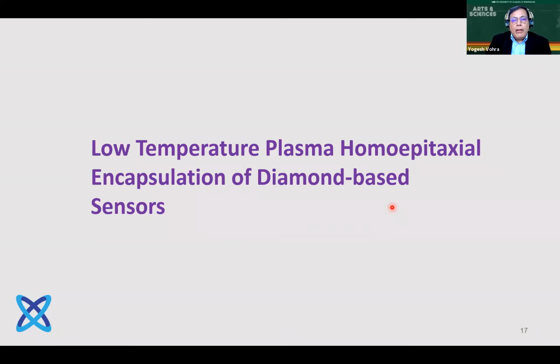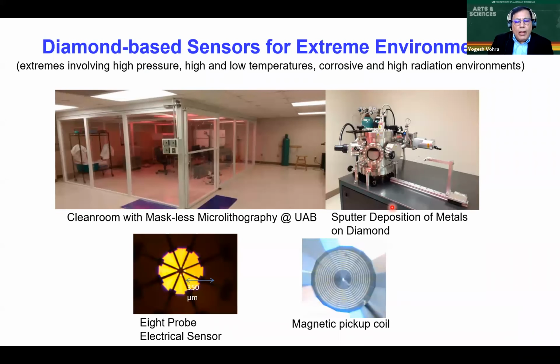Okay, so moving on to the next area about this homoepitaxial, continuing with the theme about growing diamond on an existing diamond substrate. We talk about homoepitaxial encapsulation of diamond-based sensors. So here we are going to do some lithography and actually put diamond sensors on top of a diamond crystal. So this is the Diamond Microfab lab at UAB. You can draw any pattern on the computer, and that pattern or circuit can be transferred onto the diamond. And this is the metal deposition, which basically is the metal which the circuits are made of.